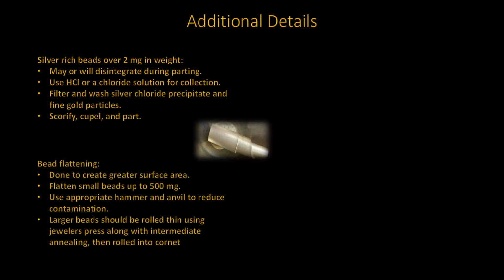The practice of flattening the bead is done to create a larger surface area for the nitric acid to complete the parting process more efficiently. Any bead that weighs up to 500 milligrams can be flattened out using a hammer and an anvil, one that will not contaminate the bead. Make sure that no slag or other forms of contamination will be hammered into the bead. Any beads greater than 500 milligrams will need to be rolled thin using a jeweler's press. Annealing will be required intermittently throughout this process. Once thin enough, they should be rolled into a cornet.